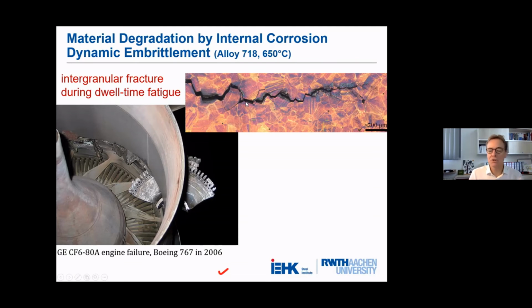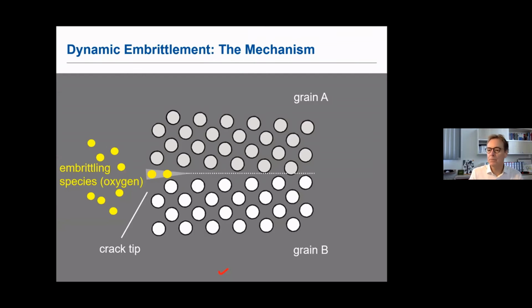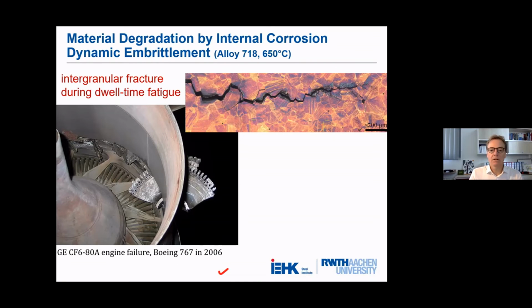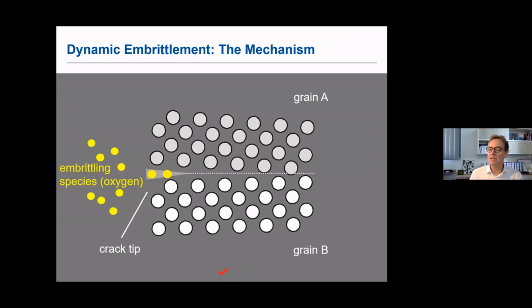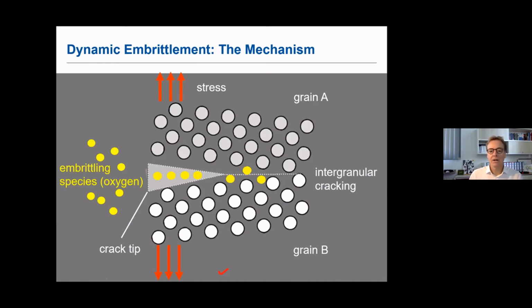This is a fatigue crack propagation rate, which is just much higher. So then we observe under dwell time conditions. Also, the mechanism behind that is that we have a tensile stress acting on the grain boundary plane, and that drives oxygen diffusion into the grain boundary, and that lowers the cohesion of the grain boundary, and then finally intergranular cracking on a nanometer scale.